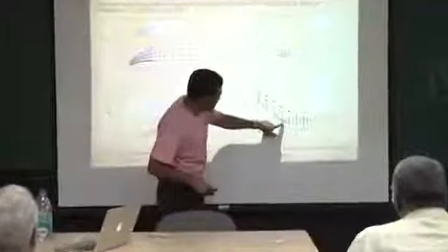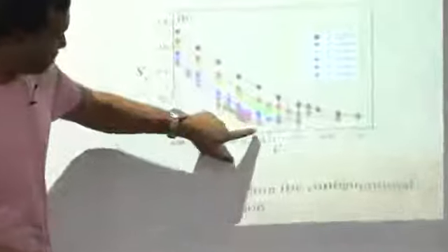And they also agree that there are anharmonic effects, but it is not clear whether, if you just add anharmonic effects, this line will become parallel to this or not. So that is a debate which is not settled, but just to find out, at least we have some clue of what is happening. So we simulated the same glass with the same system size at these state points, where, let us say, at a given temperature around 12% pinning, entropy goes to 0, and at some other temperature around 15% entropy goes to 0.